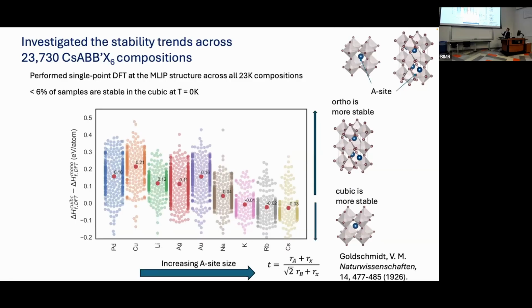And what was surprising to us is, in terms of the number of compositions in this space, about 24,000 compounds, there's a really small subset that at 0 Kelvin are actually stable in the cubic phase, which, as I mentioned in the introduction, was one of the main phases that's been used as a template for screening these large spaces. So what this means, of course, is if you change the structure, you're going to change the stability. You're also going to change the band gap energy in particular. So if you're screening materials for, for example, photovoltaics, then you're going to be particularly concerned with whether or not the cubic is the ground state.